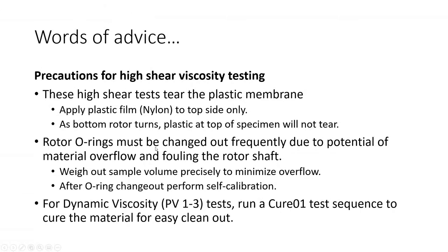All right. And then because you don't use plastic on the bottom and the rubber is basically getting into the shaft area, you have to change out your rotor O-rings quite often. And so you weigh out a sample precisely to minimize the overflow.